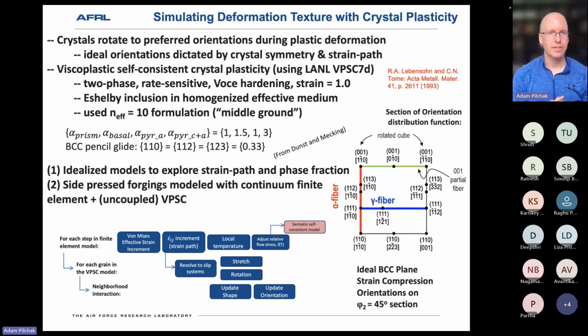So we went to the VPSC code to try to simulate some of these effects and determine if we could predict the instances and the cases in which this rotated cube orientation would form. I realize I'm probably running out of time, so I'm not going to talk through the details of the VPSC code. I refer you to Ricardo's paper that covers it in great detail. We took well-established ratios of critical resolved shear stresses for that, and then ran both idealized models where I systematically varied the strain path and phase fraction to explore those effects,